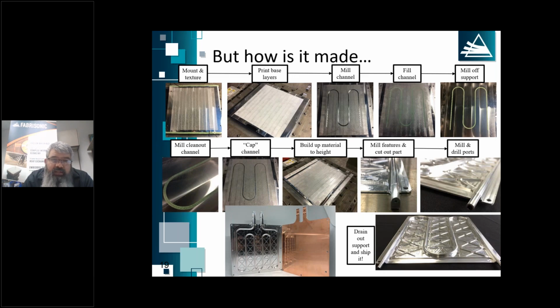Just to give you kind of a range, these parts here were helium leak check tested down to 10⁻⁹ standard cc's a second of helium. So that's kind of space flight qualification numbers. Burst pressure tests on these parts were about 3,000 PSI, and operating, I think, was only about 200, 300 PSI.